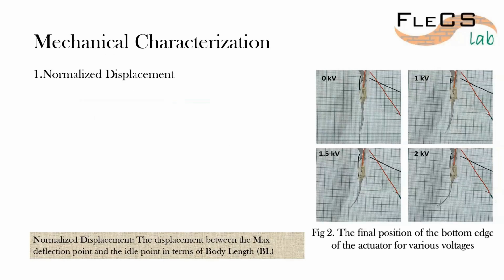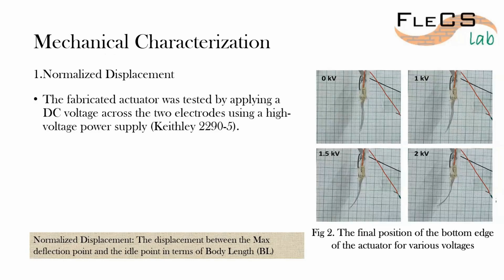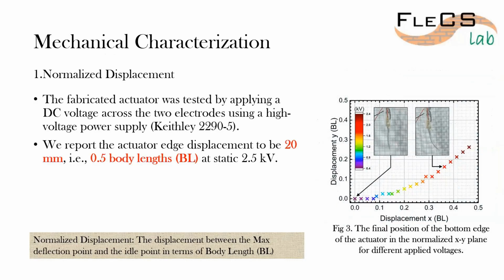So we basically did this study where we had the flapping wing characterized for how much displacement we are getting at what applied voltage. And we figured out that we are getting something close to 0.5 body length. Body length in this case is 4 centimeters, the length of the flapper. So that is how much we are getting at around 2.5 kilovolts static.